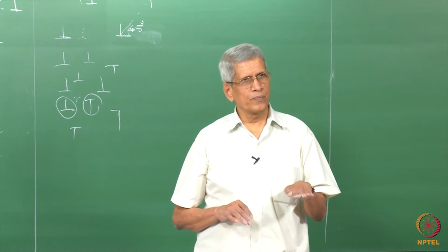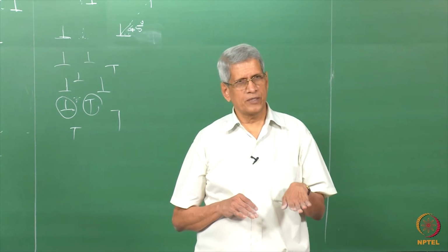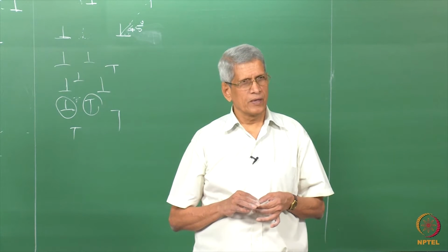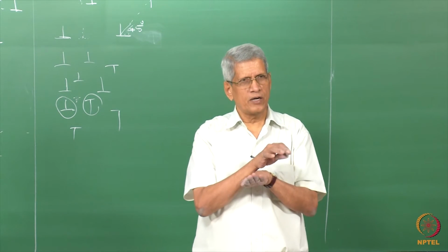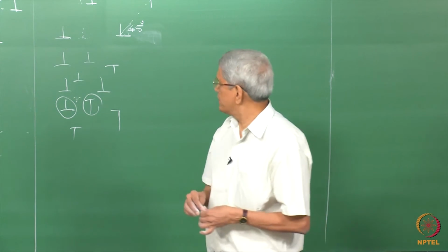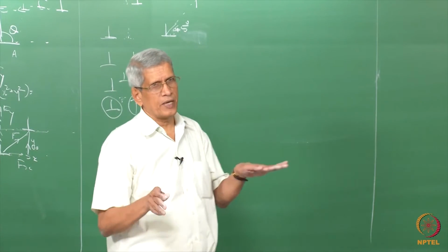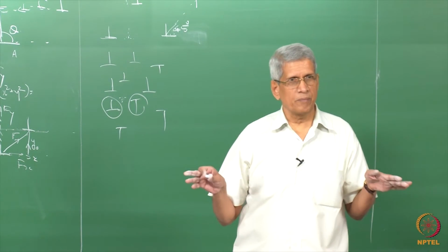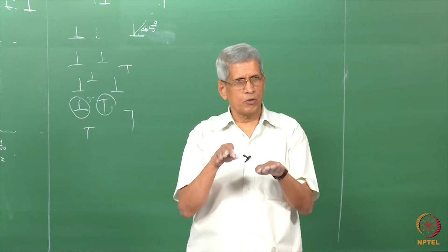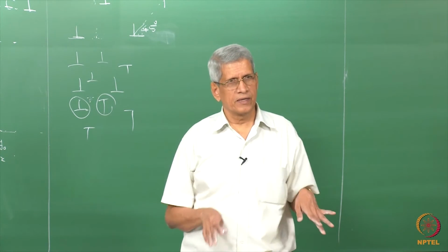Now I want to reduce the hardness, for which I take it to a temperature close to 0.5 Tm, to anneal it. Then these dislocations will start moving and rearranging themselves. In that process, the positive and negative dislocations, because the numbers need not be the same, right. The density of dislocations with positive Burgers vectors and negative Burgers vectors need not be the same, but they will be moving and cancelling each other.